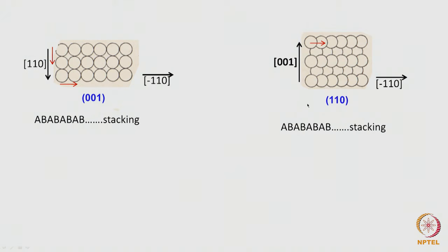And if we take the 110 plane, these are all the atoms on the 110 plane. This is a close packed direction, and this is the -110 direction which is not close packed, and the layer of atoms shown is actually the layer behind this. So only one close packed direction is there. Suppose in this plane the dislocation has to move, then it will be the 110 plane, but the Burgers vector will be 1 bar 1 0. That is a possibility.